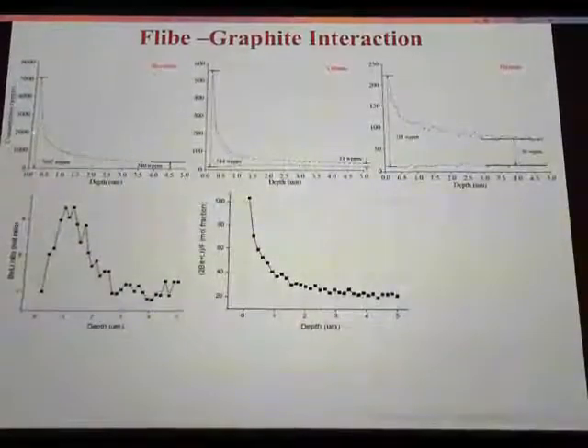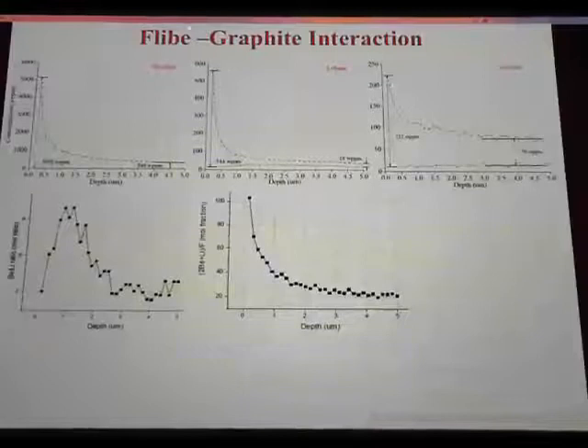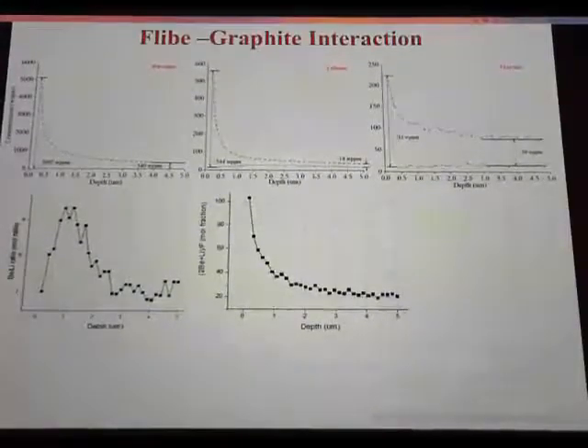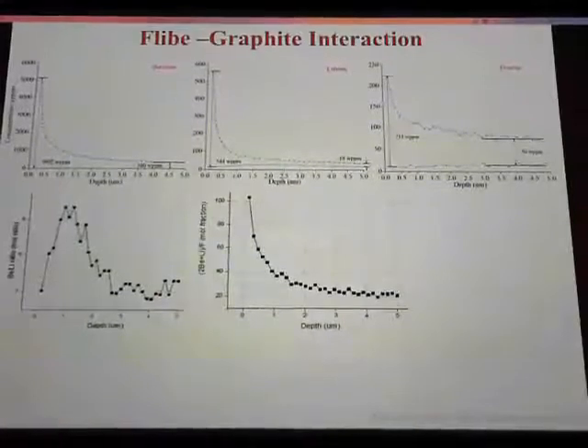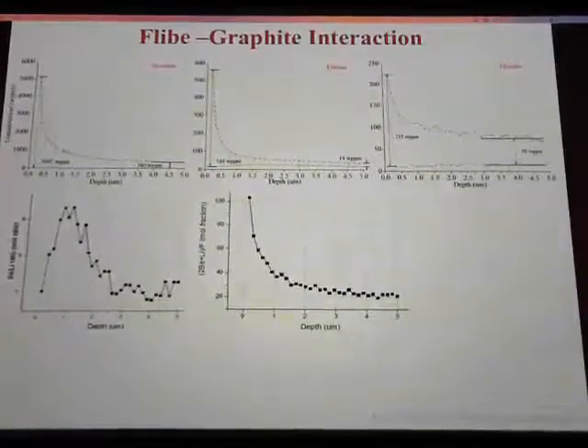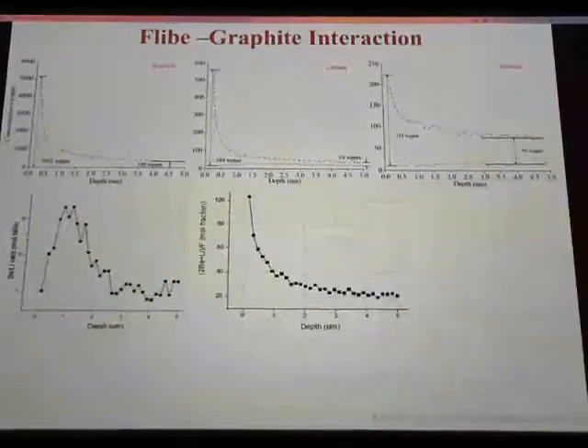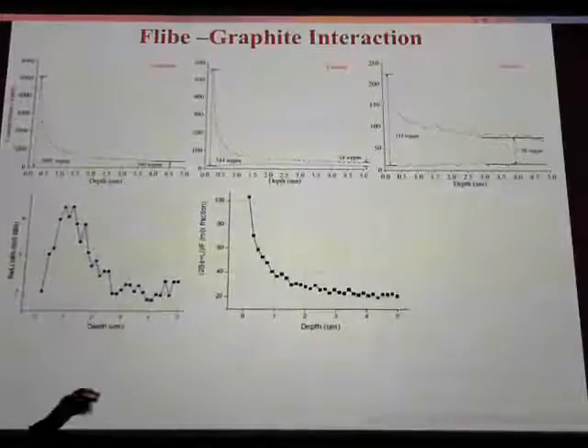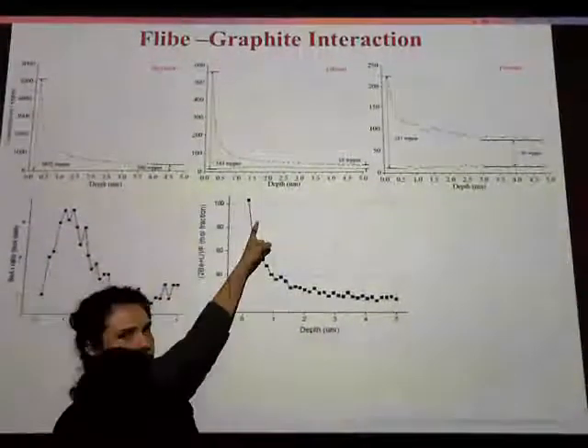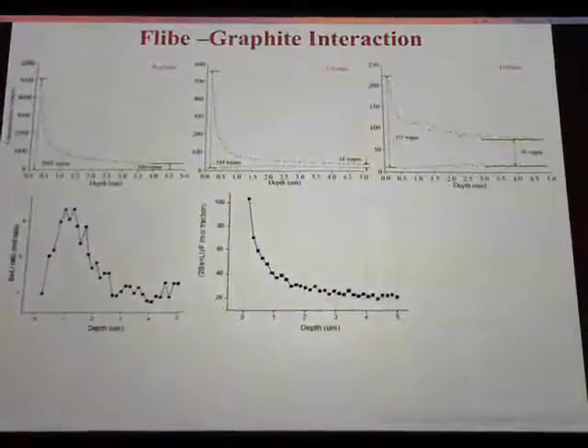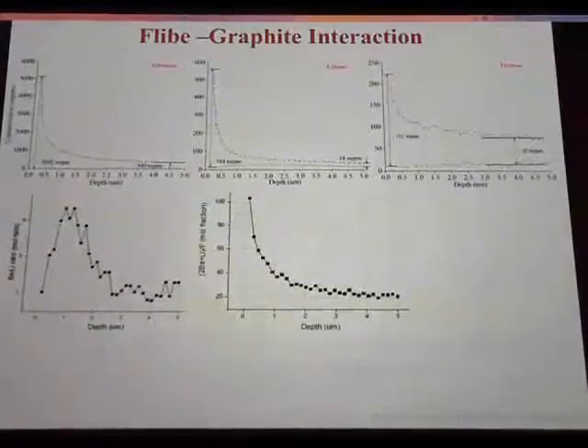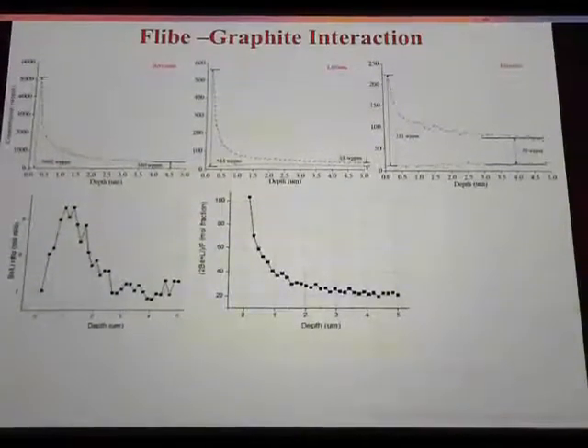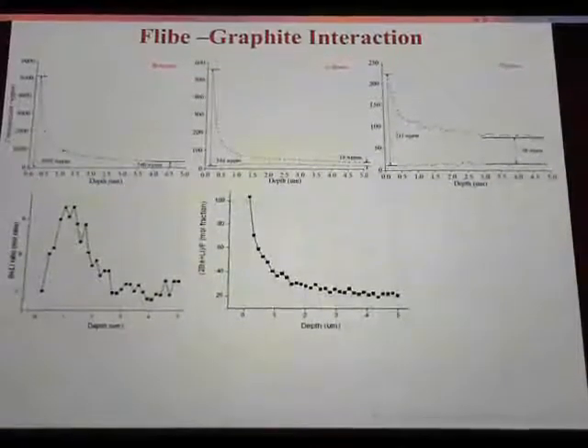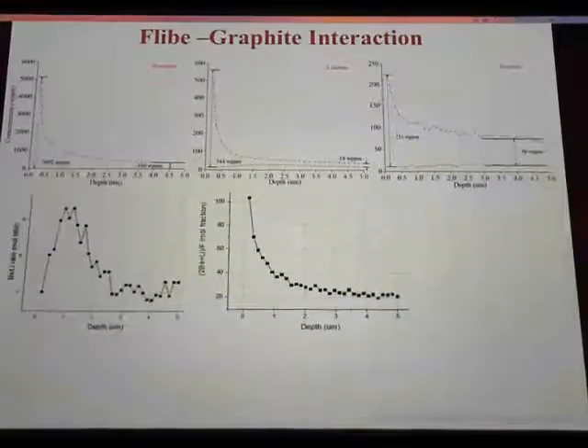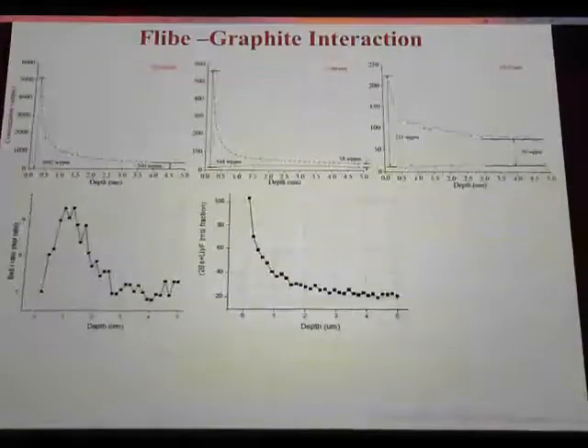Mass spec shows us that we have beryllium, lithium, and fluorine down to at least 5 microns. And okay, something's happening, something's going in. But what we just learned yesterday, this is data from yesterday, is that the metal to fluorine ratio is 100. So we either have metals or carbides or hydrides, but we don't have fluorides, which, yes, I agree with the reaction. So, fascinating.